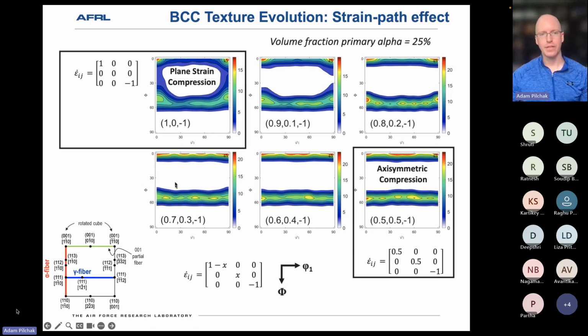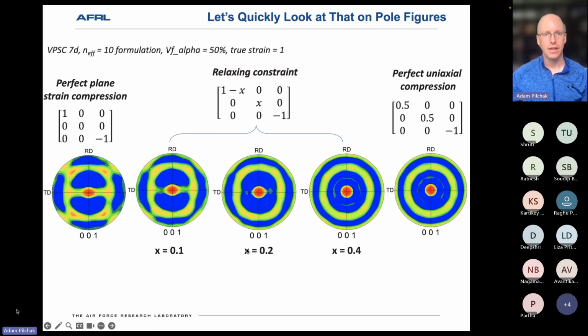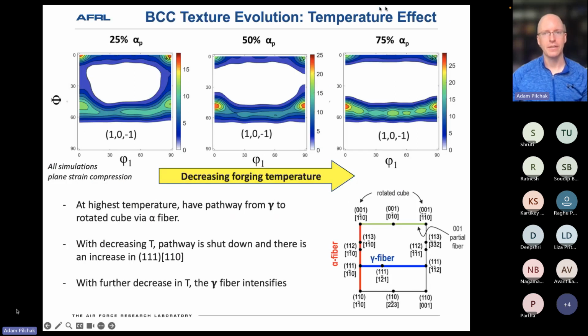By the time I let 30% go, I have a pretty uniform distribution of orientations along this top one here, called the 001 partial fiber, and you can see the progression. So it's telling us that there is something unique about that strain path that's allowing more orientations to get to that rotated cube than anywhere else. That's the same thing on pole figures, so I'm not going to dwell on that.